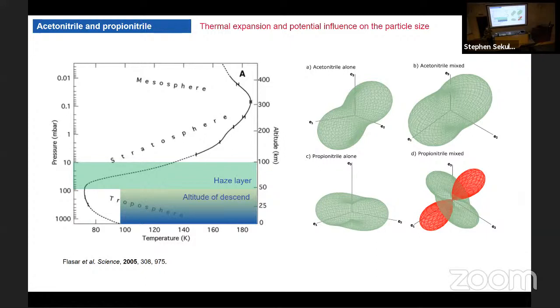The differences in temperature would cause crystals to expand and shrink. If this shrinking and expansion is anisotropic, it can easily lead to fracturing of the crystals. If you have fracturing of the crystals, the spectroscopic data that you're collecting will be influenced by that fracturing, which is completely normal because the scattering will be different from a fractured surface compared to a nicely polished surface, and that might explain why we see Titan the way we see it, very fractured. Again, further theoretical analysis in this case is necessary to really understand how this fracturing works.